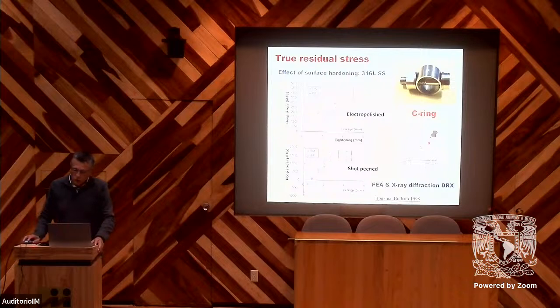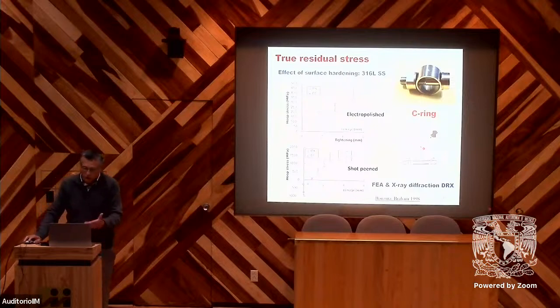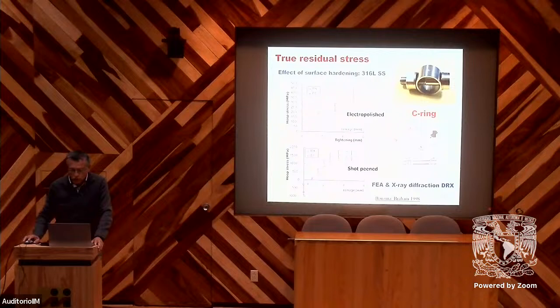So if we remove the surface layer affected by machining, for example, or by shot peening, we can see here the evolution of the hoop stress as a function of the depth in millimeters. We can observe, for example, for 5 millimeters, that we have at the surface about 350 megapascals. But now, if we take the same test with after shot peening, we can observe that with a depth of 5 millimeters, we have 1,500 megapascals. This is due, of course, to the hardening of the surface.